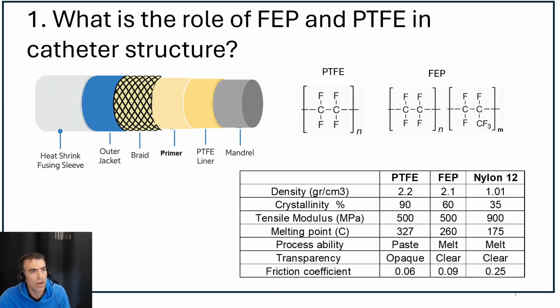To move the outer jacket better toward the primer, we use a layer called heat shrink, and that heat shrink layer is made of FEP. FEP is a copolymer of PTFE and another polymer, polyhexafluoropropylene, so it has 6 fluorine groups in it and 3 carbons. Adding that segment into the PTFE to make it a copolymer changes the structure of PTFE completely. PTFE cannot melt; you cannot process it via melt extrusion. But FEP, with the addition of that segment, is extrudable. You can extrude it, and if it's heated, it can melt.